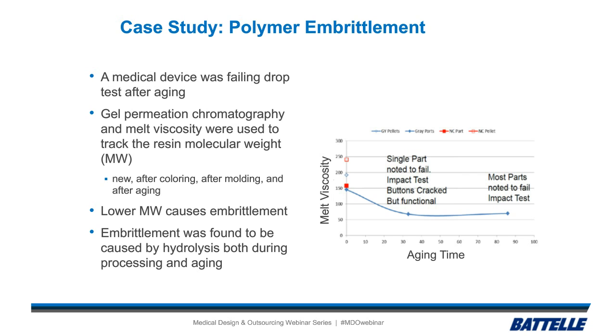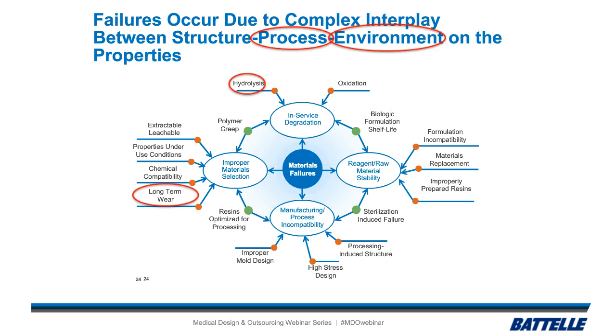So what we found is it decreased very much during each one of those steps, and what the suggestion was is we should do the coloring and the injection molding at the same time to reduce the number of processing steps and therefore keep this material more tough with less hydrolysis so it doesn't break during a drop test. So as far as I know, that's been working out well for this product, is by reducing one of those processing steps, we're able to shift that entire curve up, and it doesn't embrittle after aging. This was a process and an environment. So the environment caused hydrolysis because there's humidity in the environment, and temperature and humidity are what cause hydrolysis. And also it was a process because we had to go back to how they colored it and how they injection molded it. So those were processing issues directly related with this material.